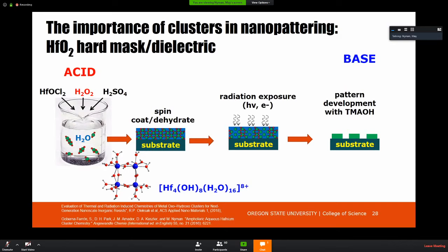This second peak is bridging hafniums within this square, about 3.5 angstroms. And then these other two peaks represent the diagonal correlations. But notice in the freshly prepared solutions, we don't see those at all. They're missing. Okay, so our hypothesis is that the peroxide chews up these squares into dimer forms, and then after time, they reform. And so we can see those diagonal relationships. Okay, but we still don't know where the peroxide is.